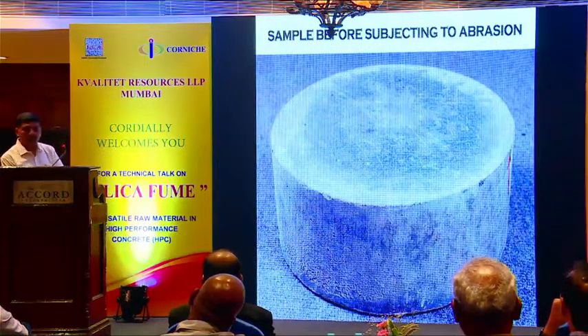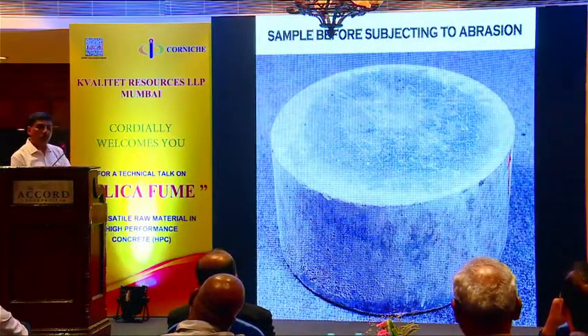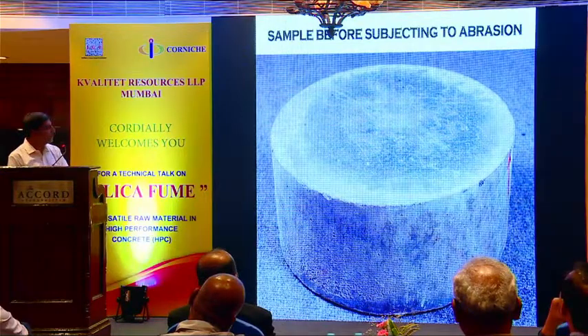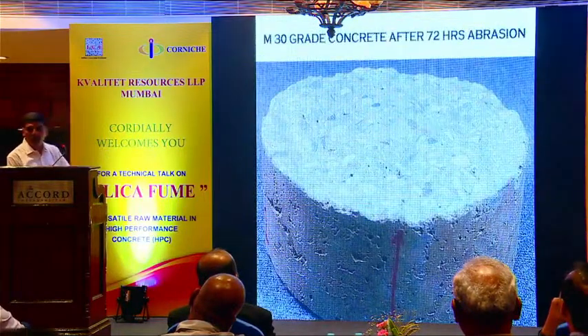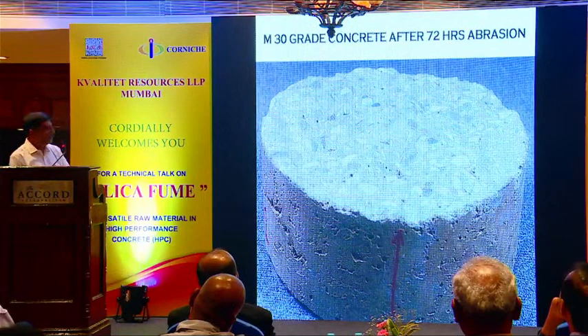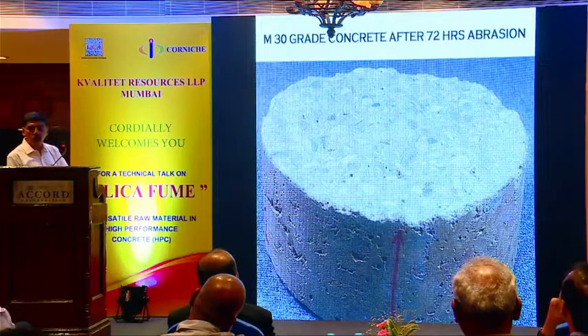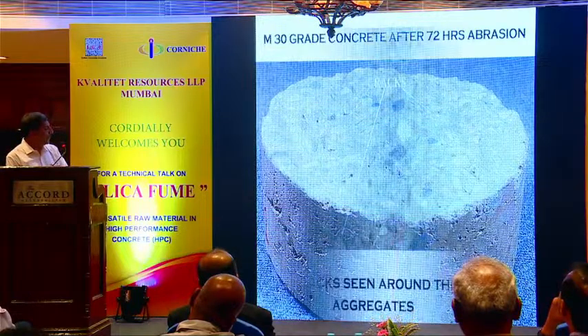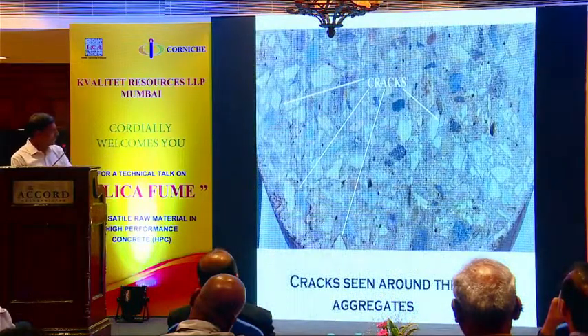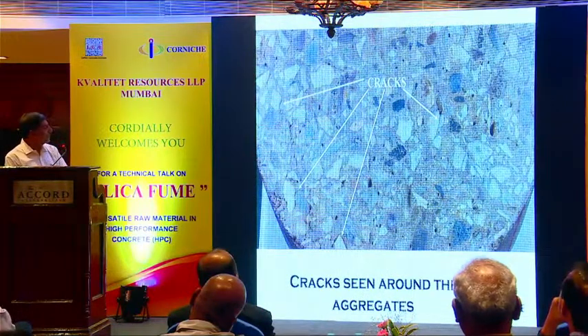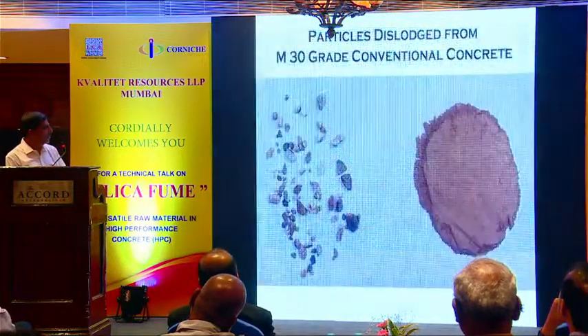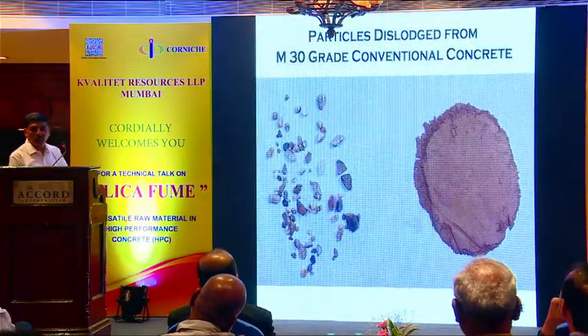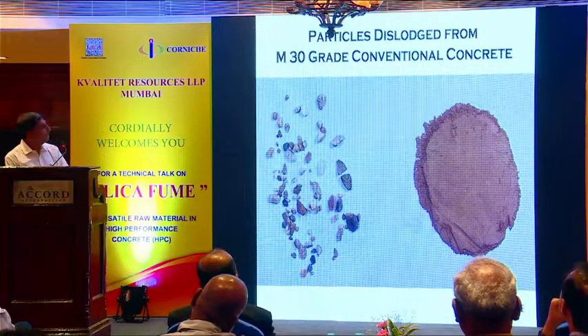This is a 28 days cured sample before putting into testing, conventional concrete, M30. After 72 hours, this was the state. Lot of wear and tear, and the bond was not good. Aggregates were peeling off because of a weak bond. You can see from closer, cracks and aggregates peeling off. We collected the residue, the worn material. You could see some of the peeled aggregates because of the loose bond in conventional concrete.